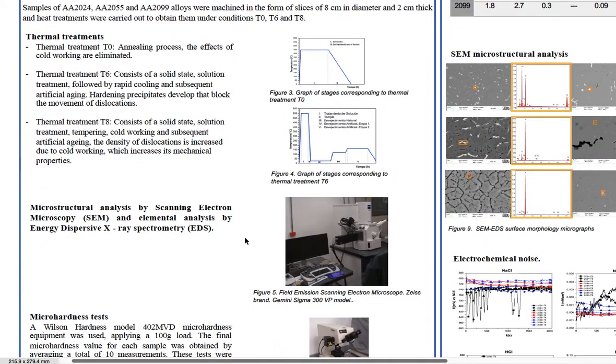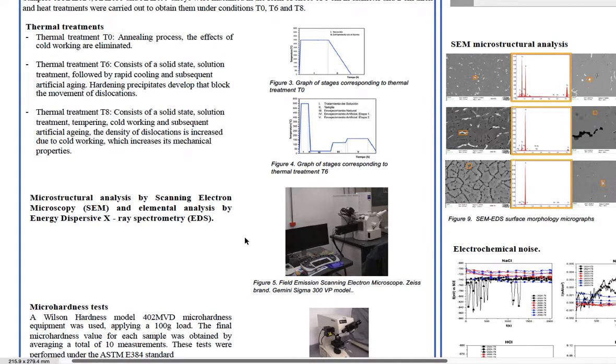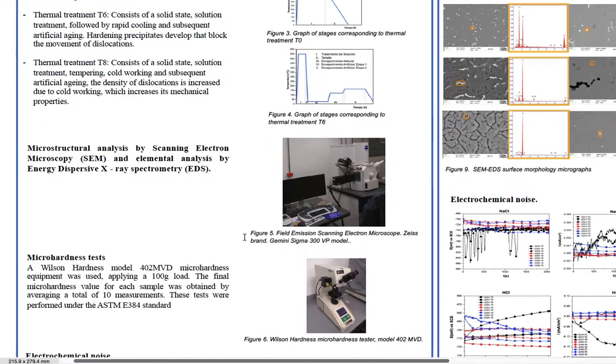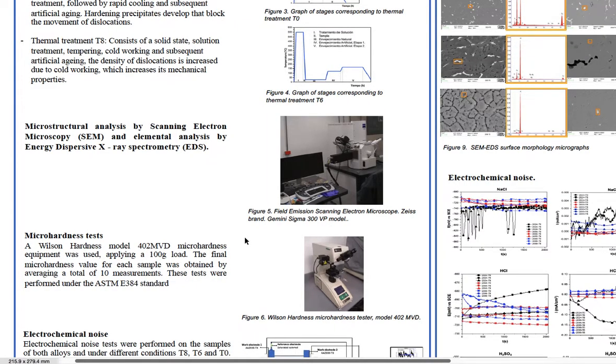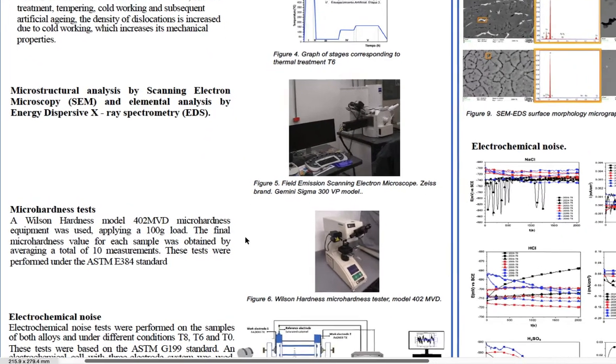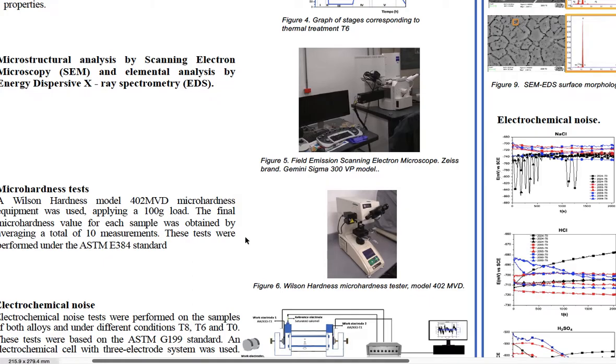Once the alloys were obtained under the three heat treatment conditions, they were prepared metallographically to be characterized by scanning electron microscopy, SEM, and elemental analysis by energy dispersive X-ray spectrometry, EDS. After this analysis, the samples were subjected to the Vickers microhardness test, applying a load of 100 grams. Here I show the standard under which these tests were performed.